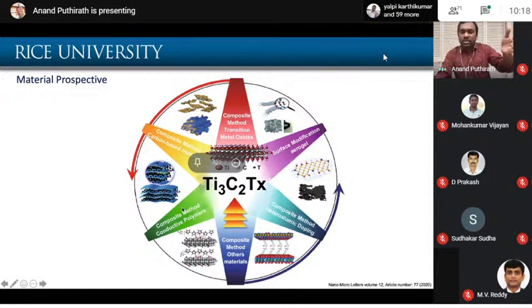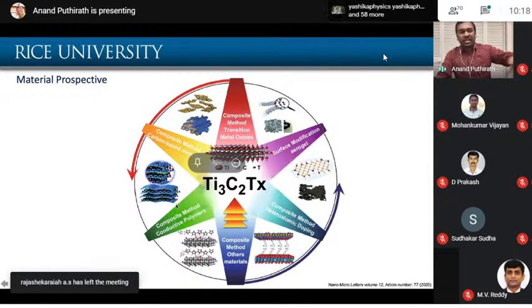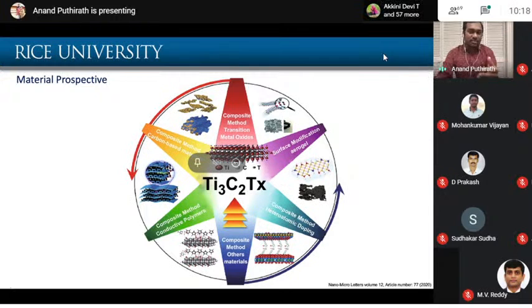And that was the kind of bottleneck associated with high surface area material. Their conductivity is very poor, so even electrons cannot come from the current collector to the material. And with the discovery of MXenes, they are still high surface area, but better conducting than conventional activated carbon or some other materials, like titanium-based nitrides or carbides. They have slightly better conductivity, but at the same time high surface area, a moderate thing. So this is the hero in the field of supercapacitance now. MXenes are showing much better behavior than activated carbon or conventional materials.